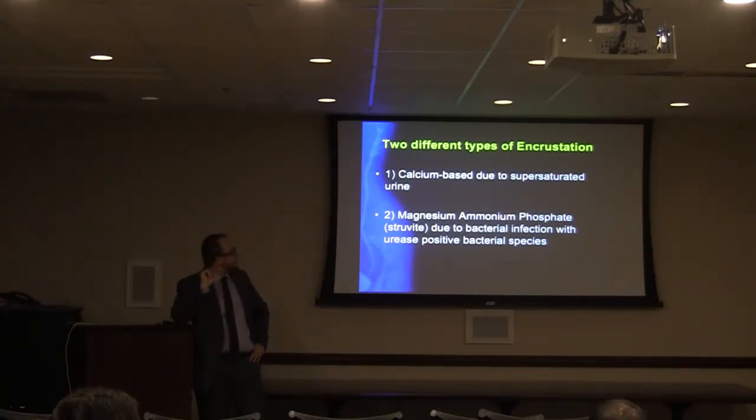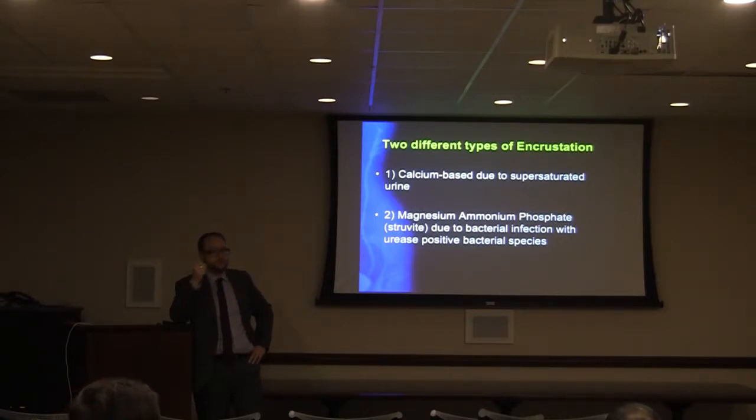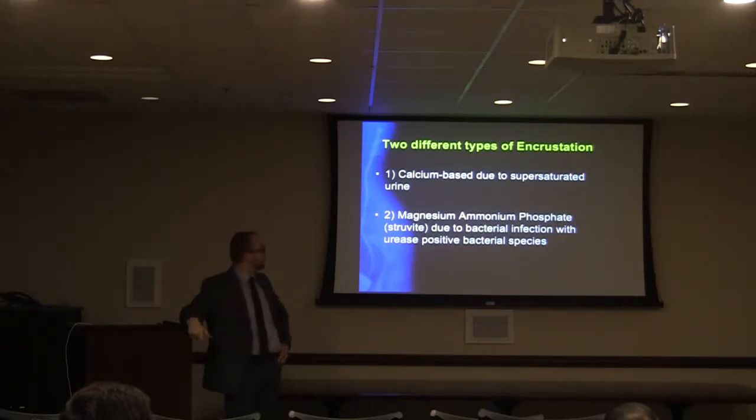Calcium stones form mostly due to the urinary environment being supersaturated for calcium and oxalate. When calcium and oxalate bind, they form an insoluble crystal. If oxalate binds with anything else, sodium oxalate for instance, that dissolves readily. But when it combines with calcium, it becomes a problem.